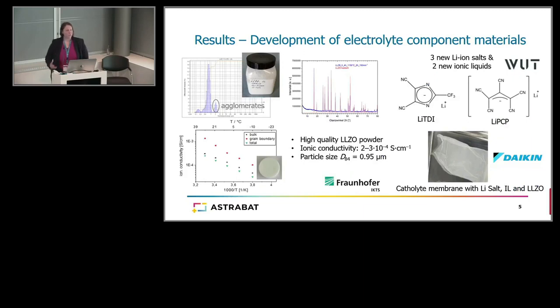In addition, we've looked at other components, or are looking at other components, to make our hybrid electrolytes, so specifically LLZO, in order to integrate into the electrolytes themselves, and then also new lithium salts and new ionic liquids. So here on the left, you can see the LLZO that's being developed with a particle size of about 1 micron. This is particularly important when we come a little bit later to some of the new architectures for 3D printing, that it is below this 1 micron size.